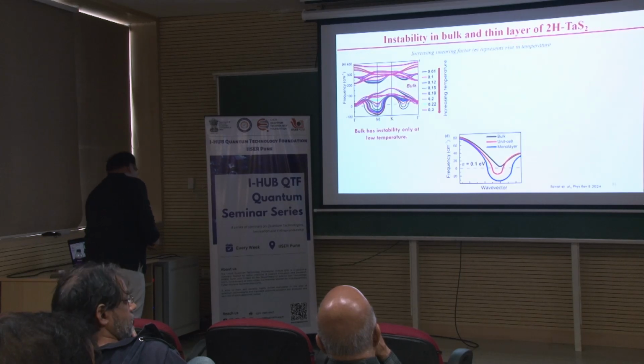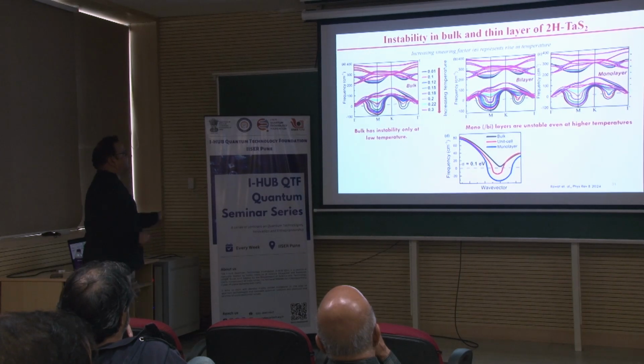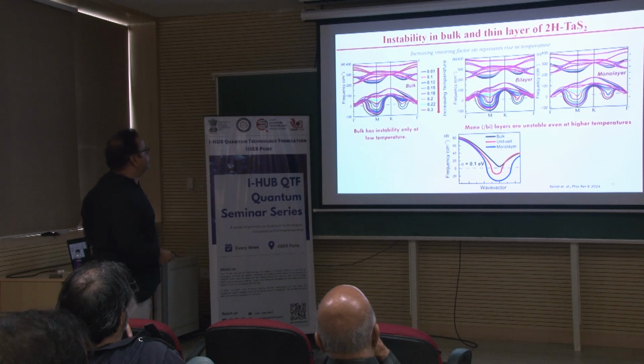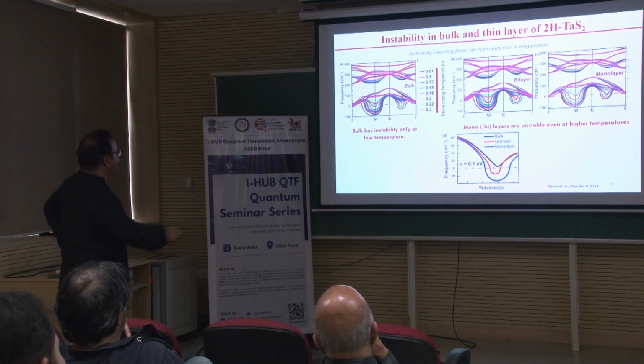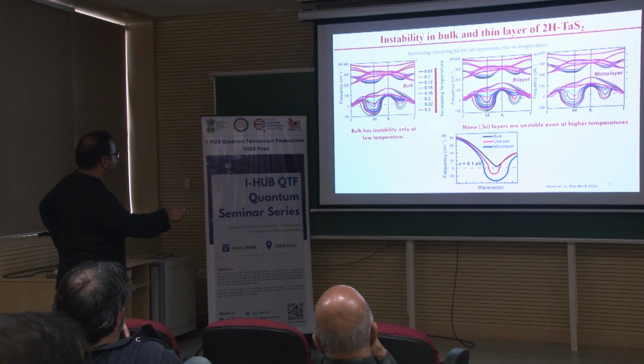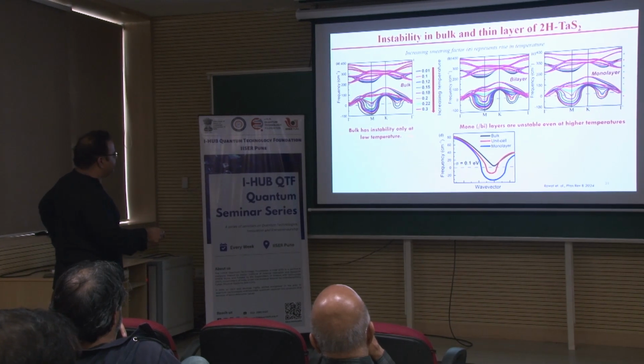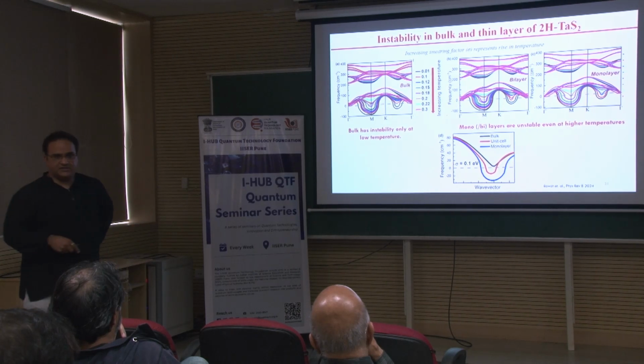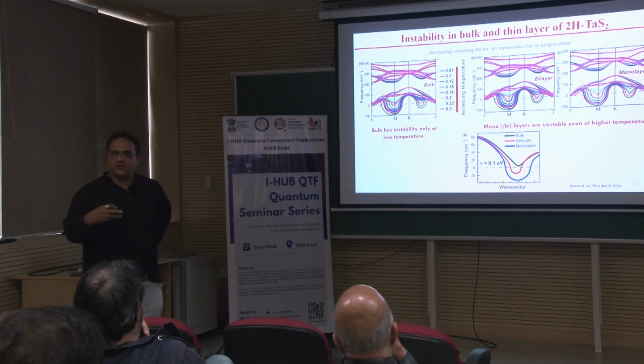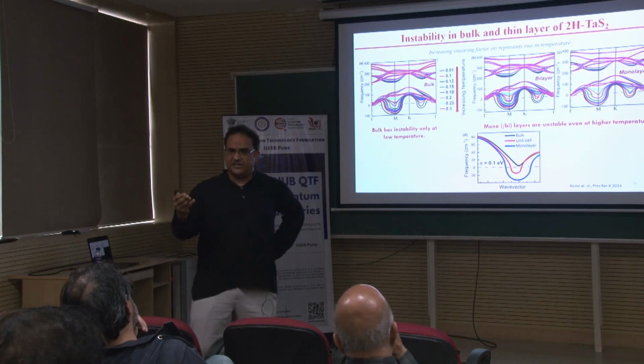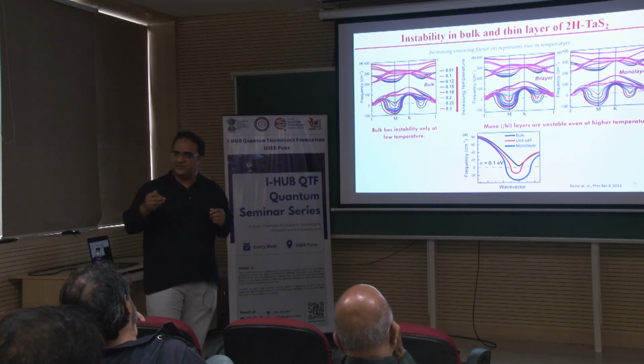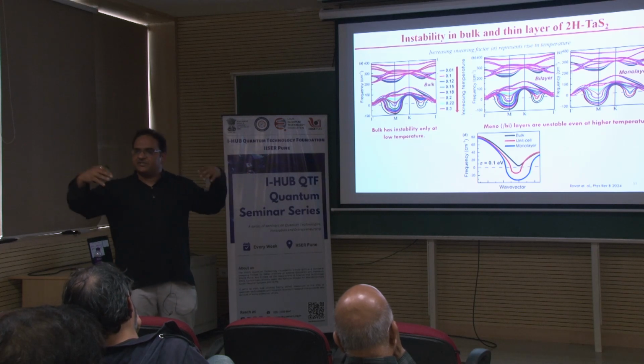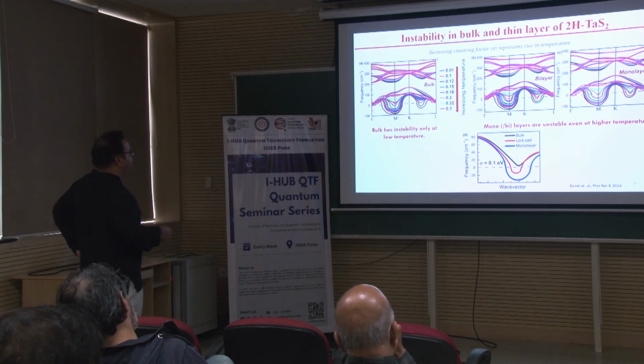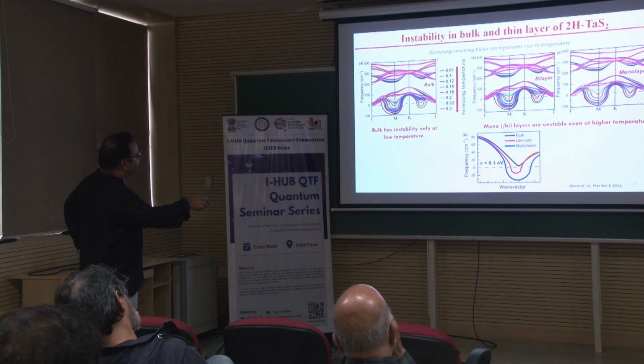Then we did some calculation, we talked to some of our collaborators, okay. So this is the phonon dispersion, frequency versus momentum. The bulk has an instability only at low temperature. And how are we changing the temperature in the calculation? We are changing the smearing factor. That smearing factor will not tell you the absolute temperature, but it will tell you the range of the temperature where the instabilities can exist. Okay. So, I am changing my smearing factor from 0.01 to 0.3 here.